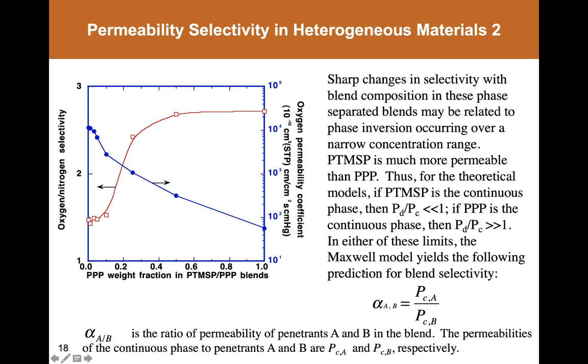And so this slide is just making the argument that if you go back to the Maxwell model or the Brueggemann model and plug in the idea that the material is continuous in one phase or the other, you will derive the result that the selectivity is governed by the selectivity of the continuous phase. So the selectivity over two gases, A over B, say oxygen over nitrogen, is equal to the ratio of permeabilities of oxygen over nitrogen in the polymer that's the continuous phase. And when you see a step change in the selectivity, that shows you're going through a phase inversion.